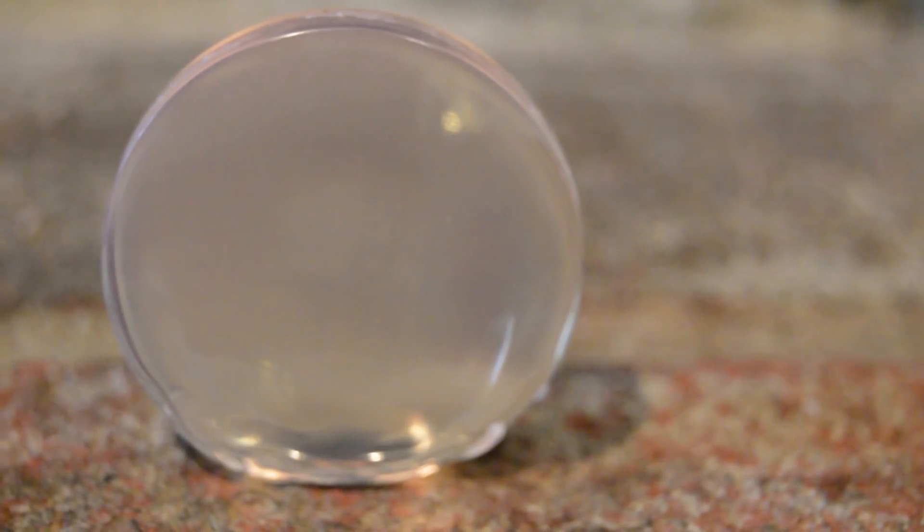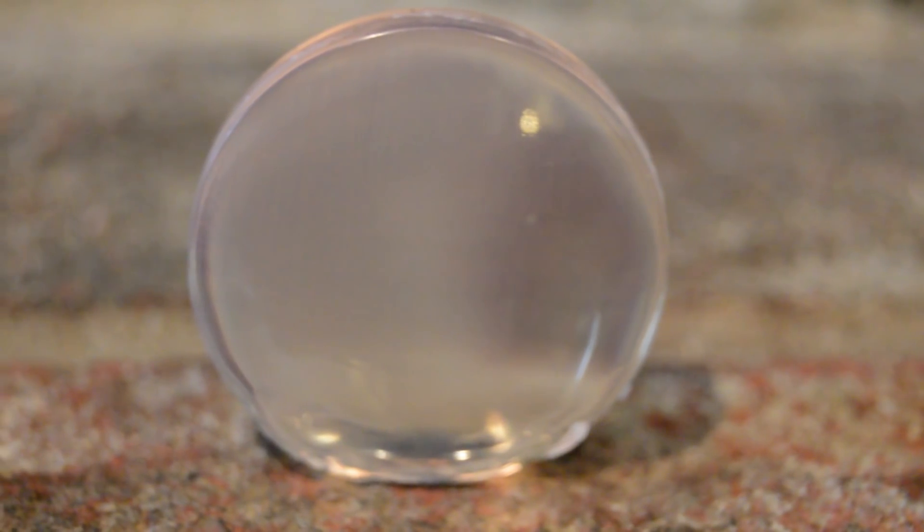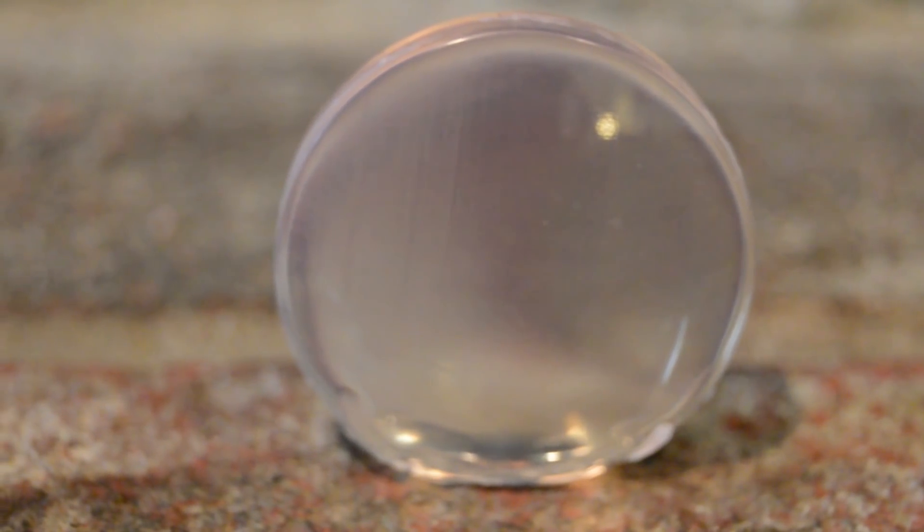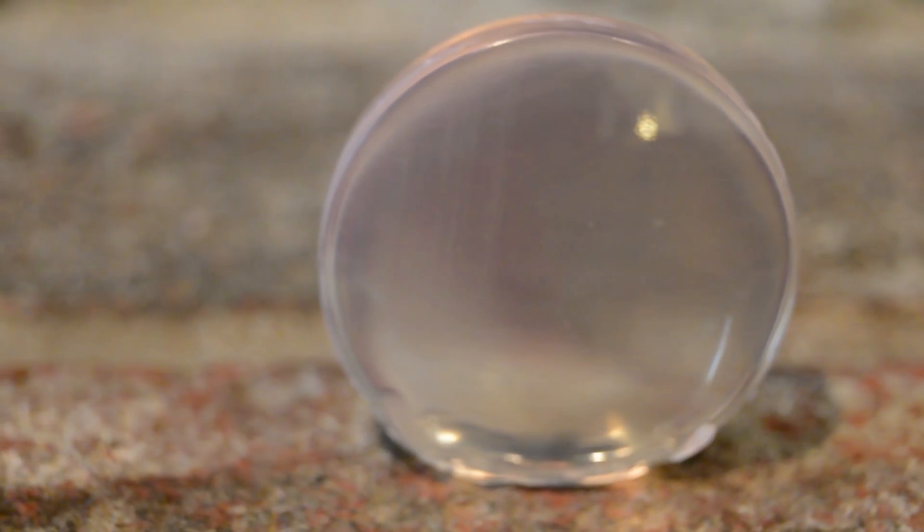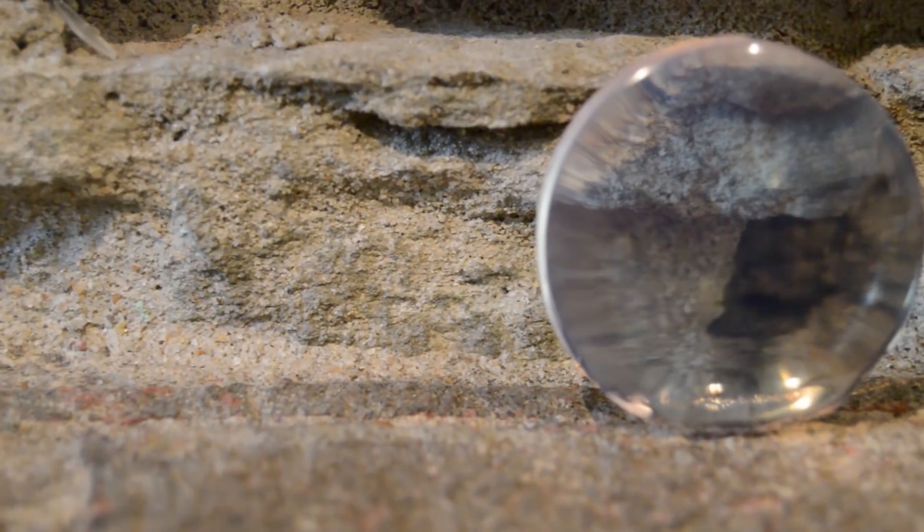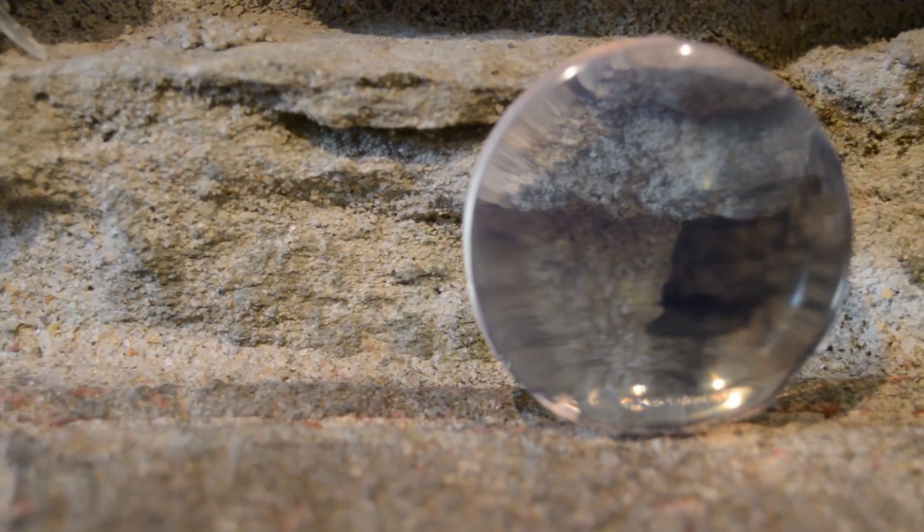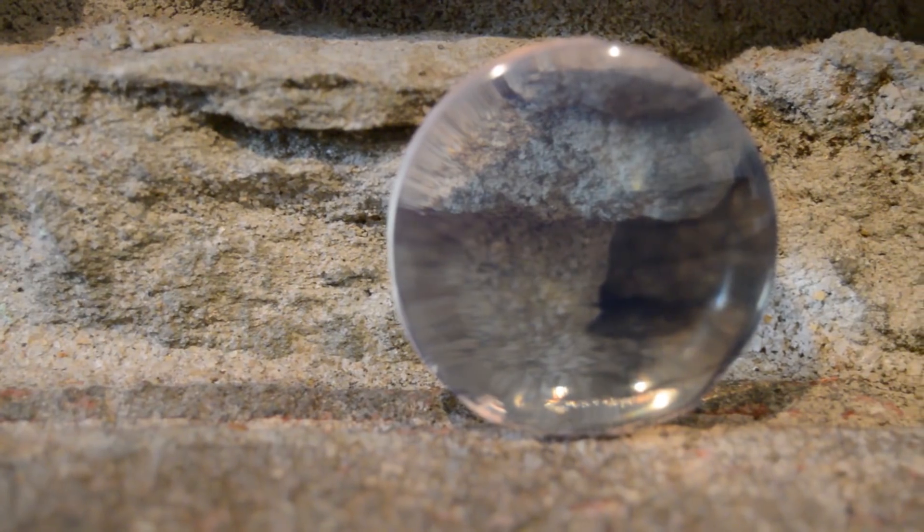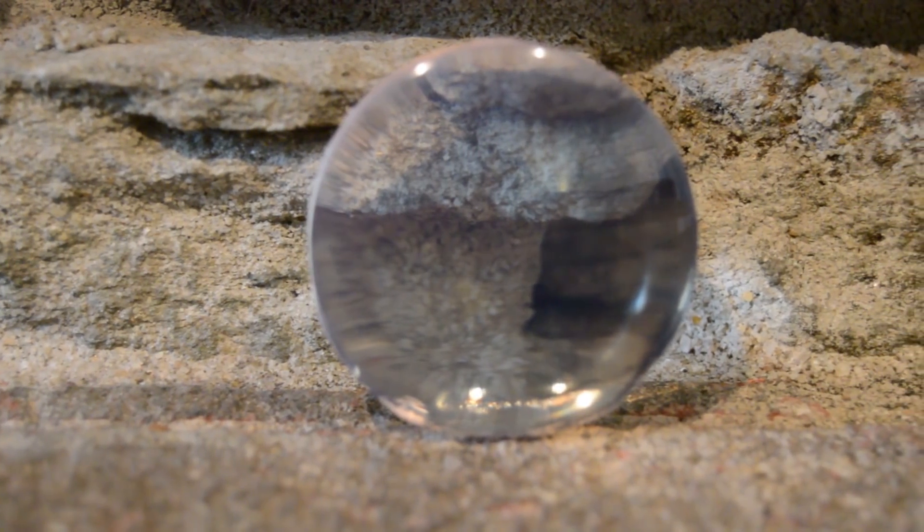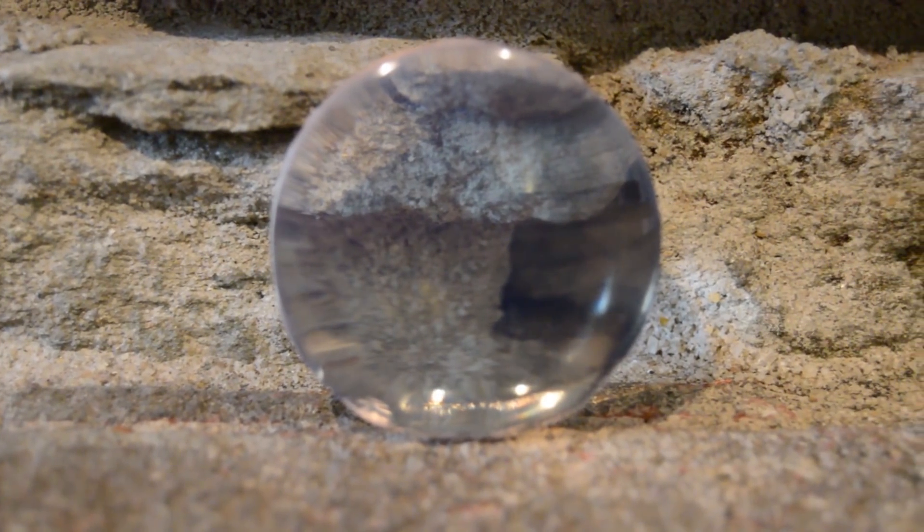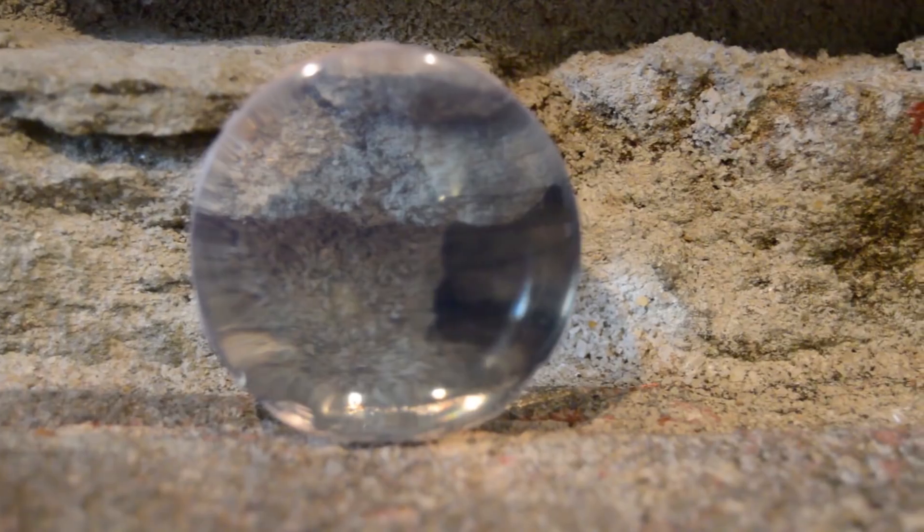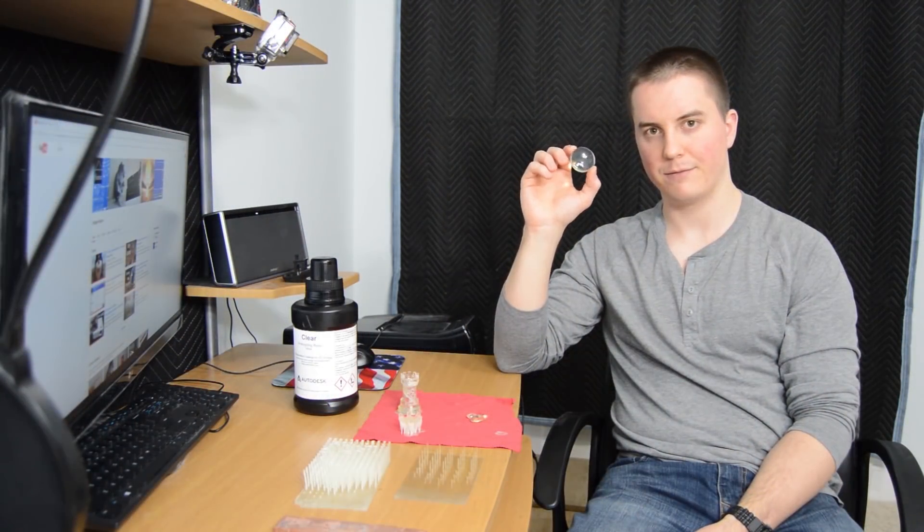After I pulled it off the printer, I hit it with 1000 grit and 2000 grit sandpaper to get layer lines erased off the surface to get it really smooth. As I did that, it clouded the surface from all those micro scratches. What I found I could do is if you dip these parts in a clear gloss finish...